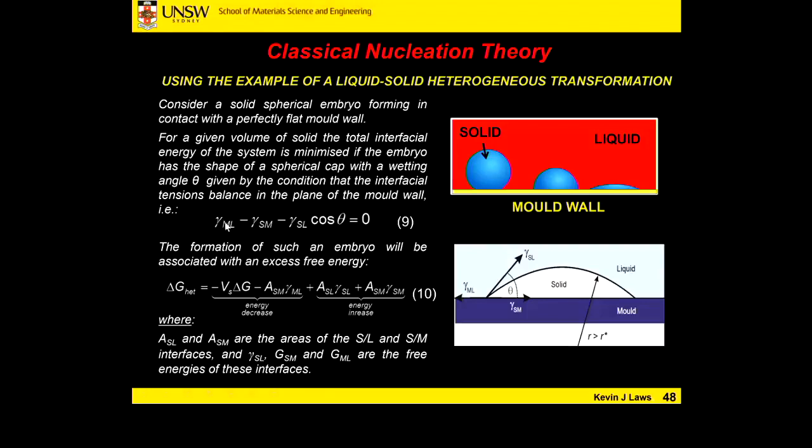So essentially our interfacial energy between our mold and the liquid, minus the interfacial energy between the solid and the mold, minus the interfacial energy between the solid and the liquid, which is the same as in our previous equations, multiplied by our wetting angle, is equal to zero. So we're under an equilibrium condition.